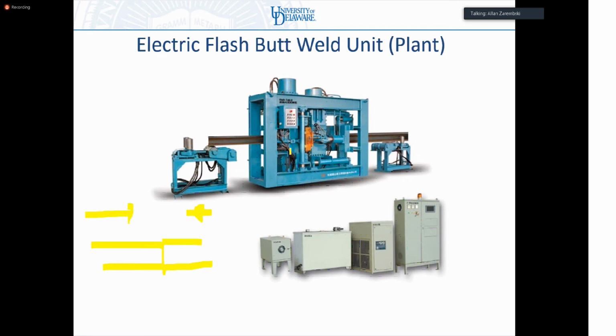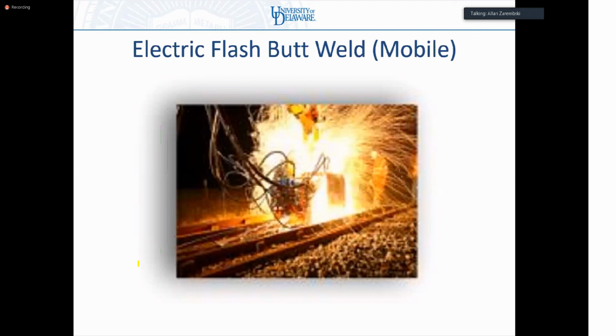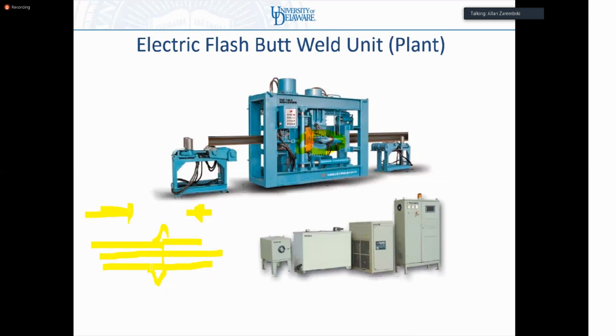In fact, I use, you can see here, these hydraulic actuators. I'm actually exerting a clamping force, pressing these two rails together, and then I'm running electric current through the rails. So I'm heating up by running electric current through the rails, applying this pressure, and then what happens is I weld this together and I actually extrude some steel. So this pressure causes some of the original rail steel to extrude outward. So I actually lose steel in an electric flash butt process. In the thermite process, I gain steel because I'm adding steel to fill the gap. In the electric flash butt welds, I'm pressing them together and then I'm extruding it.